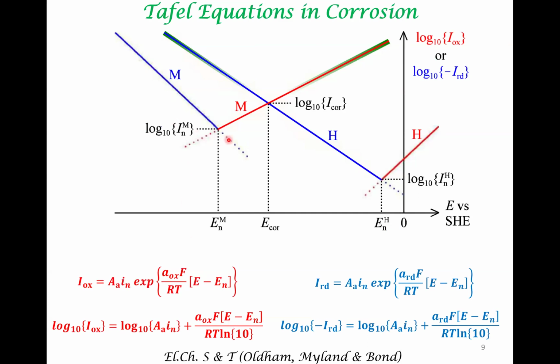So that is what is being plotted here. Again, in this plot, three quantities are important: null potential, E corrosion, and null potential corresponding to the cathodic reaction. E corrosion is the potential of the metallic sample which is getting corroded. At this potential, the rate of generation of electrons via an anodic reaction is equal to the rate of consumption of electrons via a single cathodic reaction, or the sum of cathodic reactions from multiple cathodic reactions.